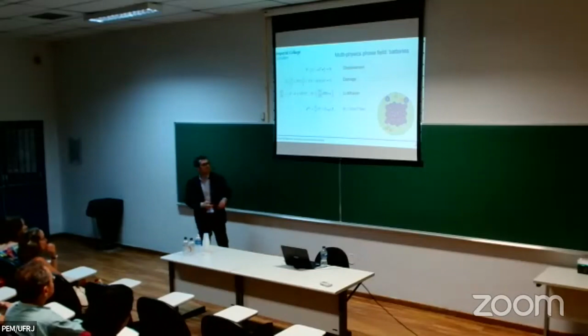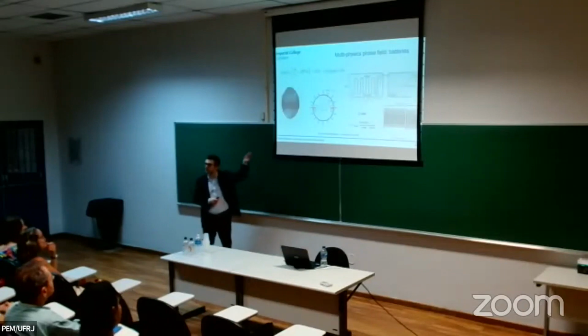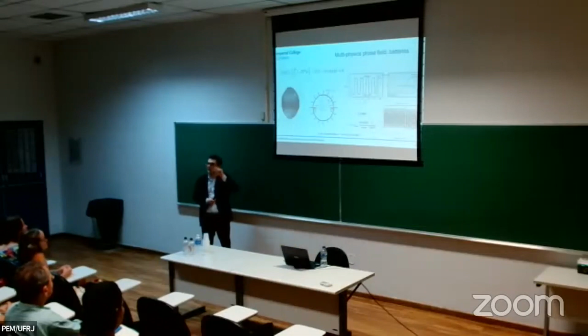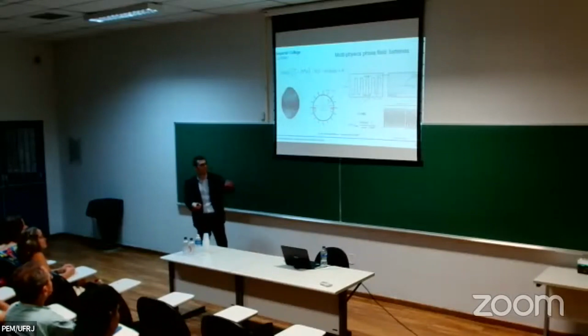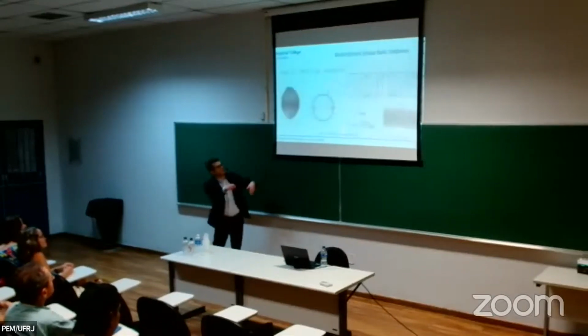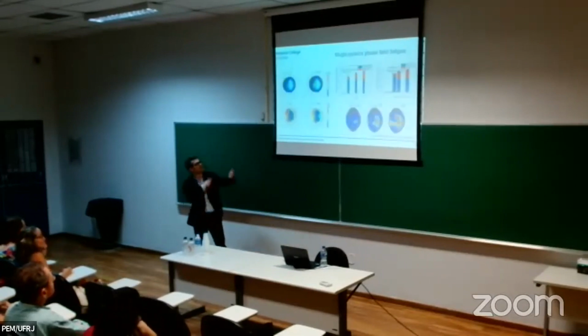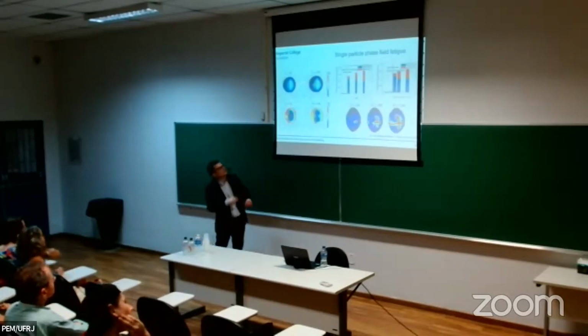Some people have used phase-field models to simulate the failure of electrode particles, but they did that only over half a cycle. But of course, this is a cyclic process. So what we did is add this fatigue degradation function and simulate the failure of these particles over hundreds of cycles, and not only looking at idealized particles, but also at realistic particles. We conducted cyclic loading over hundreds of cycles, and you can see some representative results here. You can see the propagation of cracks in both idealized and realistic particles.